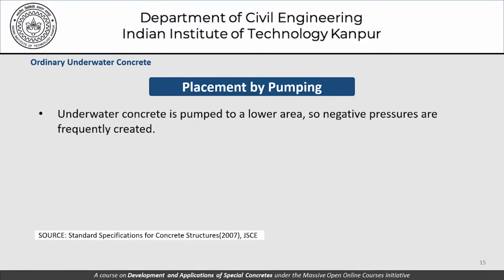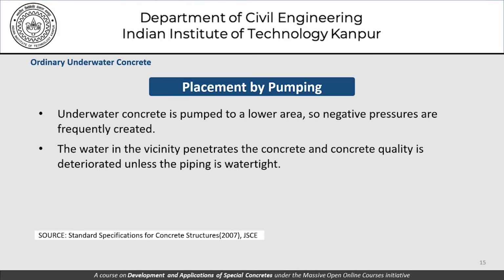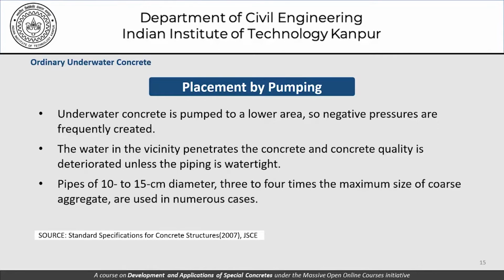When we are trying to place concrete by pumping, underwater concrete is pumped to a lower area, negative pressures are frequently created, and the water in the vicinity penetrates the concrete and the concrete quality deteriorates unless the piping is watertight. So pipes of 10 to 15 centimeter diameter, which is 3 to 4 times the maximum size of the coarse aggregate, are used in numerous cases.